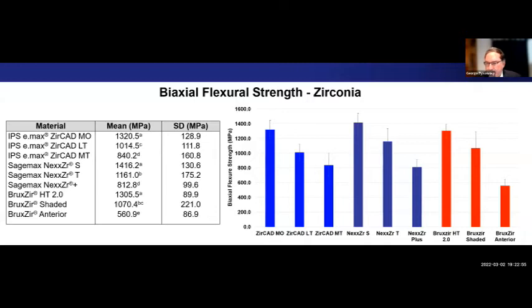We have another one, NexxZr S, which is a 3Y material. The T is again a combination of that, and the Plus drops into about the 4Y material, the NexxZr Plus. BruxZir HT is again a 3Y material. As we get into shading of it, it moves into the 4Y material and drops down to about 1100. And the BruxZir Anterior, which is a 5Y material, you can see is below 600. So knowing which brand and which material you use is very critical to the success of that final restoration.